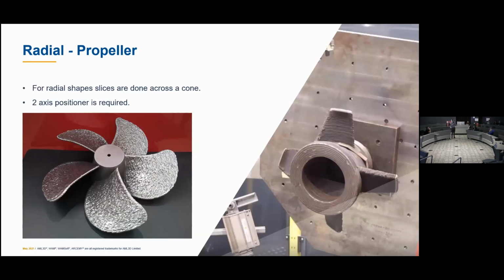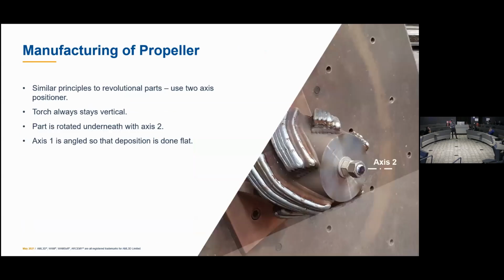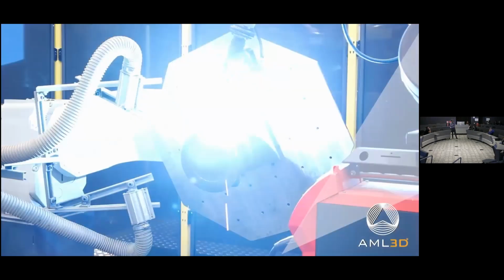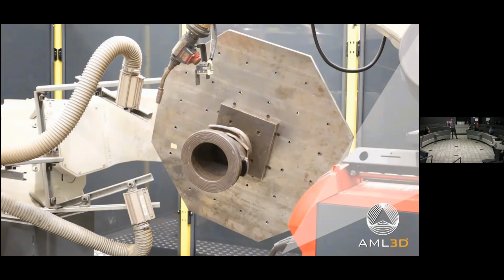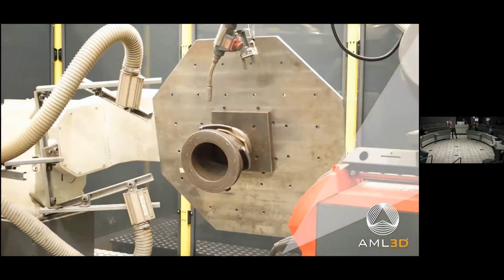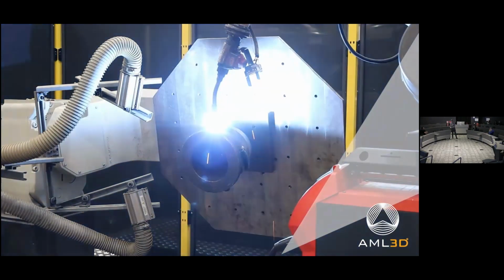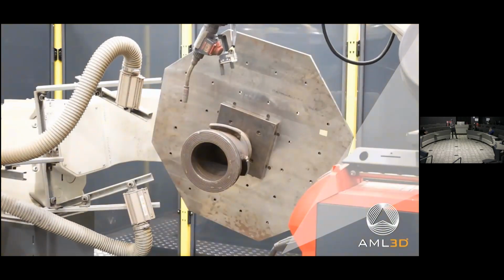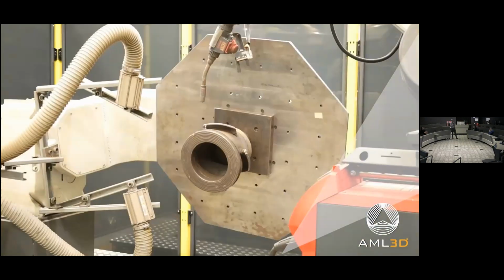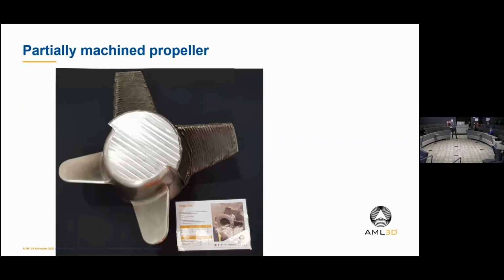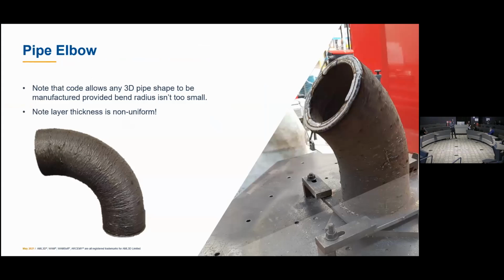So the slice in this case is on the surface, with a cylindrical surface, and once again we're using our positioner, and then rotate. Apart from the machine that we developed, we can also do 5 axes, and with the layer thickness, you see the layers go around the pipe, and the layer thickness is non-uniform.